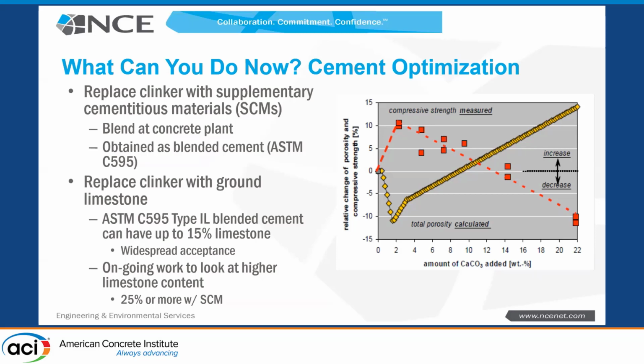So we have a 6-sack mix in our concrete, 564 pounds per cubic yard. We're going to replace 20% of that with fly ash. That's a big savings right there. We're going to maybe do 25% or 30%, or we're going to go further. We're going to now blend some limestone in there, right? An ASTM C595 Type IL.